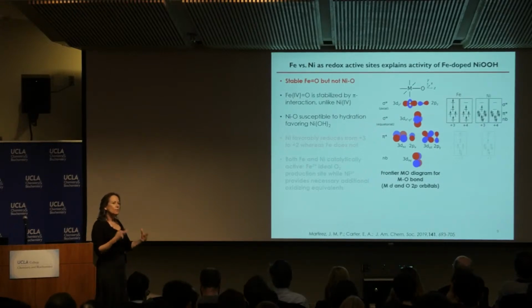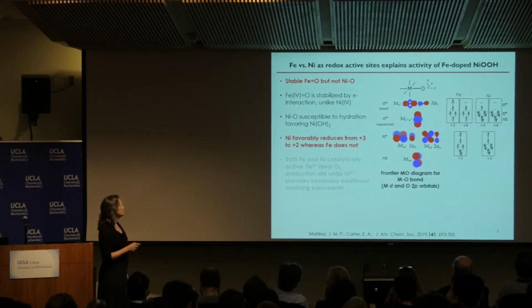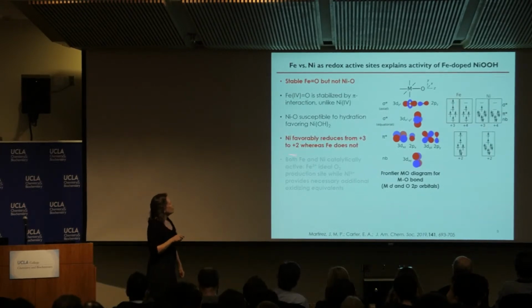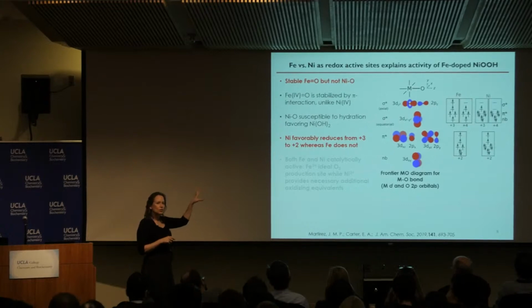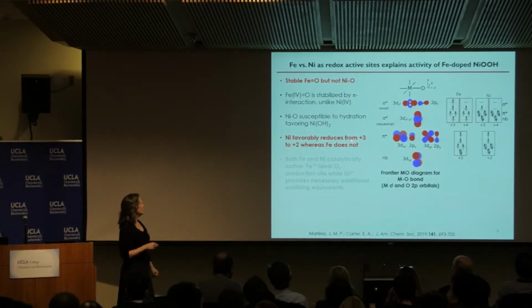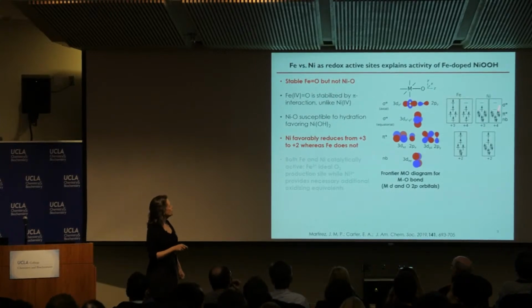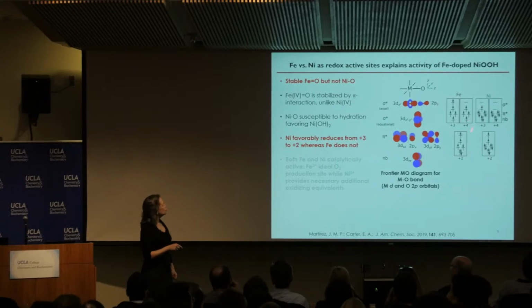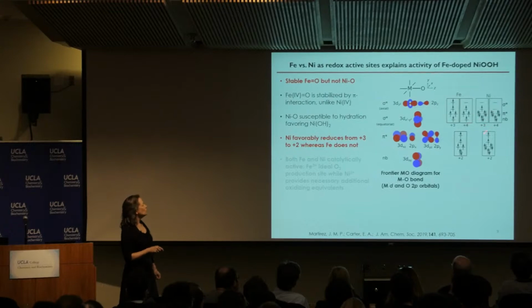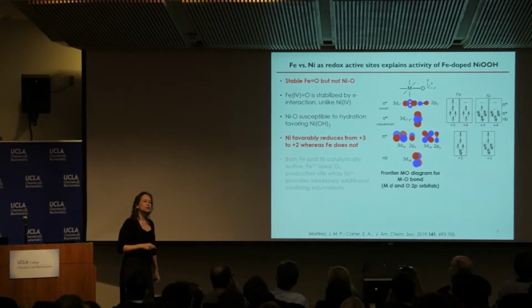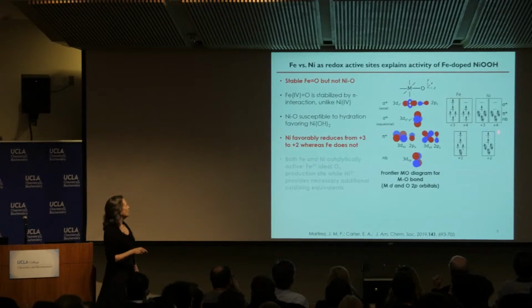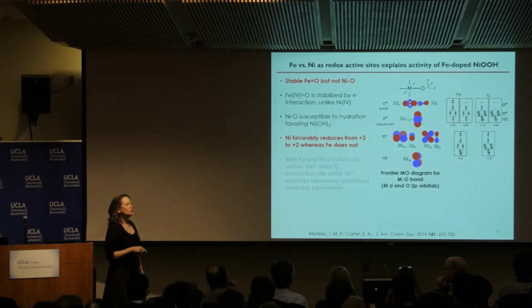But then the question is, what about the whole oxidation step itself? Well, it turns out if you think about nickel, one of the things that was true on the previous slides, which I didn't emphasize, is that nickel favorably reduces from +3 to +2. It goes from this low spin nickel 3 to a high spin state in the nickel 2 plus during the catalytic reaction. Whereas iron 3 plus doesn't want to go to iron 2.